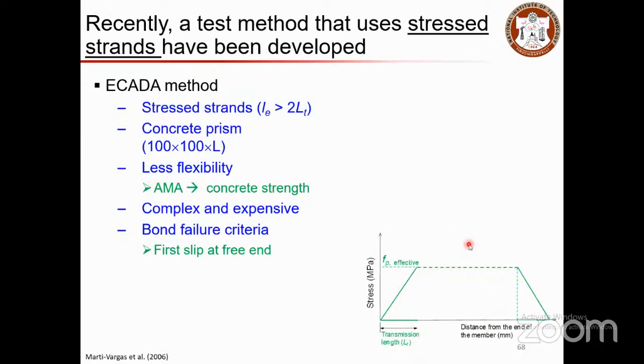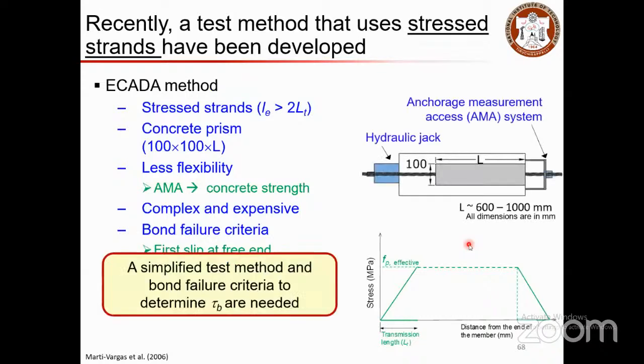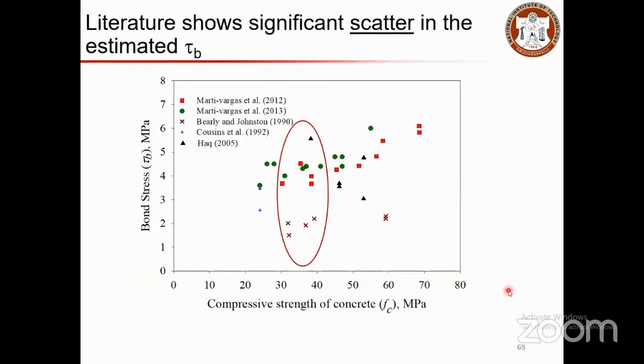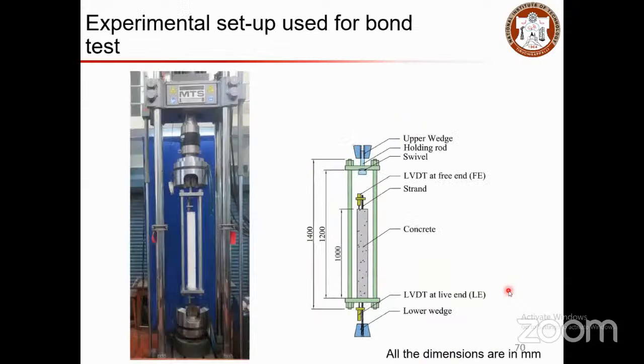Then the ECADA test method came up, adapting an anchorage measurement access method. This setup is basically replacing the stiffness of the entire remaining length of the specimen, so this involves a lot of complications and is expensive also. So we decided to come up with a simple test method for determining the bond criteria. Based on that, a simple test method is proposed, and a 1 meter long prism specimen is cast with a stressed member. The stress level is 0.7 fpu, and then the whole setup is placed in this huge MTS machine to do the pullout test.